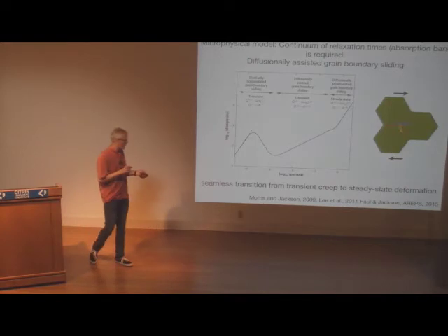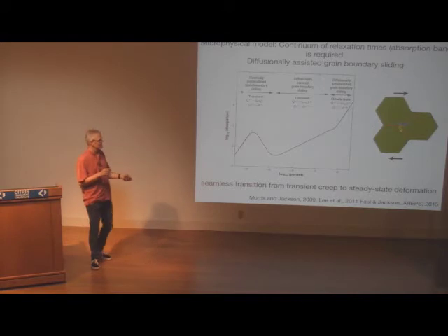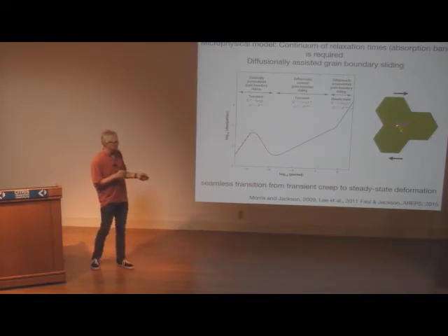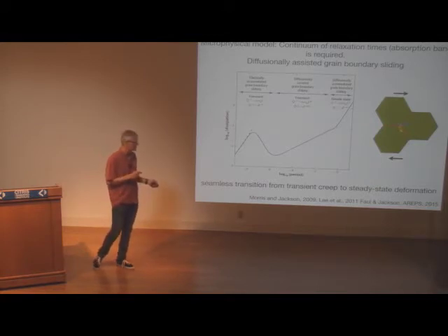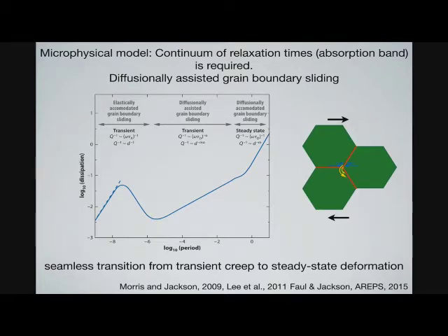And if you then put it together as a function of period, you get this diffusion, because you have different scales. The longer you apply your stress, so period increases to the right, that's log period, so time scale increases to the right. The longer you apply the stress, the further you can diffuse, so that eventually you transition into viscous behavior. You have normal diffusion creep. But in this intermediate time scale in the anelastic behavior, you have this dissipation, the energy loss or attenuation, increasing